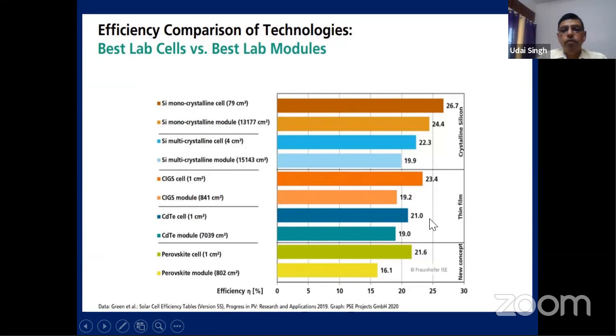Cadmium telluride 1 centimeter square gives 21%, but the module can give you 19%, so the difference is not too much. Whereas for perovskite, the highest achieved is 21.6% at 1 centimeter square. What you have seen earlier may be less than this area, so here you are comparing 1 centimeter square or more. And the perovskite module gives you 16.1%. So this is the lab scale, and how are we going to convert it into a module? What is the difference coming?